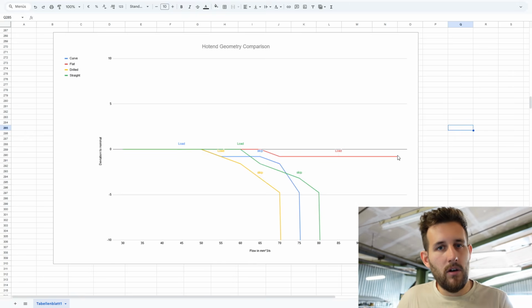With this kind of G-code, I wasn't even able to make the extruder skip. So what this tells me is that I cannot derive a definitive number off of this, but I can see that this is a significant improvement over all the other things. And with our approach of SLM printing our hot ends, it is no problem to integrate that into our melt channel geometry. Okay, well then, very shortly to my design methodology.